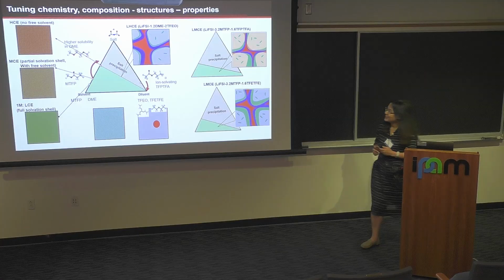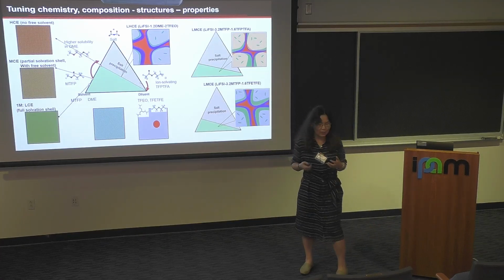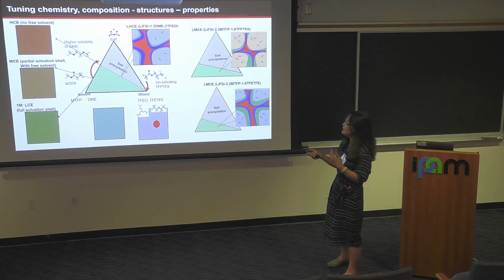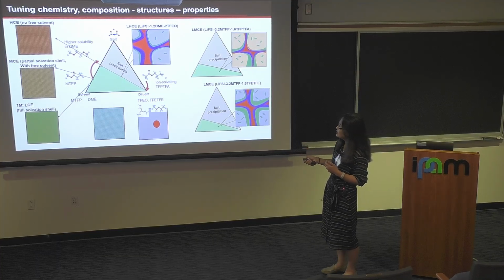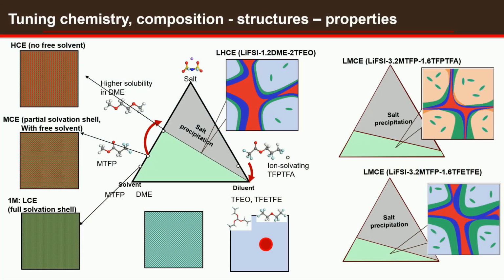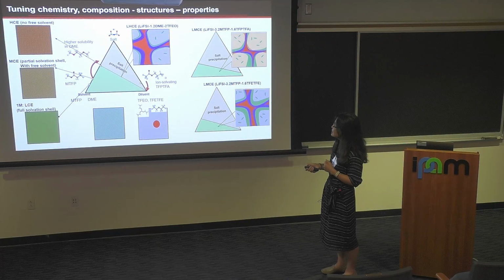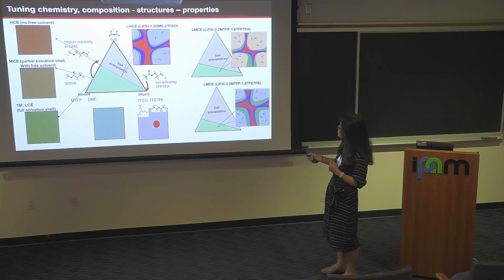So this also gave us more ideas on how to design electrolytes. We have a salt, solvent, and diluent, right? So we want to push the solubility as high as possible, but of course not all the solvents will have such a high solubility. In this corner, the diluent and the salt have zero solubility, so the diluent will never get into the solvation shell of these ions. We also looked at some other electrolytes and found this solubility plays a very important role in determining the nanoscale structures in the electrolyte.